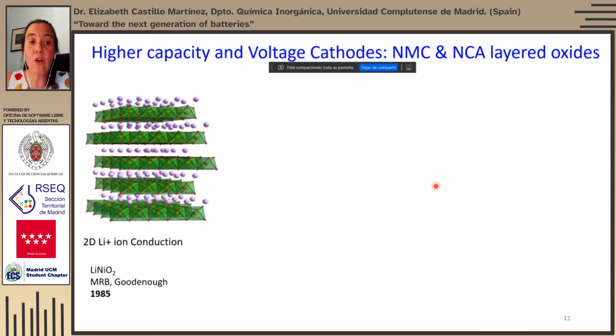Starting from the lithium cobalt oxide, replacing cobalt by nickel led to higher capacity, because in lithium cobalt oxide, only half of the lithium ions could be reversibly extracted. With nickel, you can achieve a larger amount of extraction.